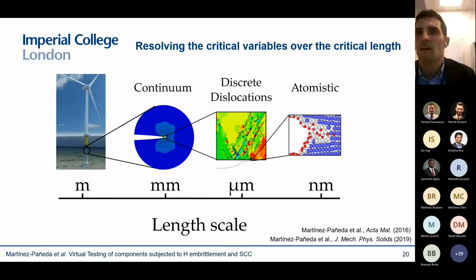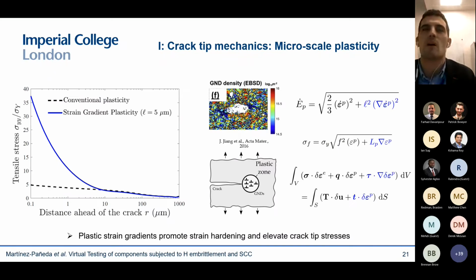And then if we go back to the drawing board, that tells me that ideally I should be using some sort of discrete dislocation methods. But again, I'm not going to be able to model this with this. So the approach that we can take is to enrich our continuum models with the physical mechanisms that we're missing at the microscale. And the physical mechanisms that you're missing at the microscales that you see when you use these dislocation models is that you have some dislocation hardening mechanisms very close to the crack tip. These are due to plastic strain gradients and geometrically necessary dislocations.